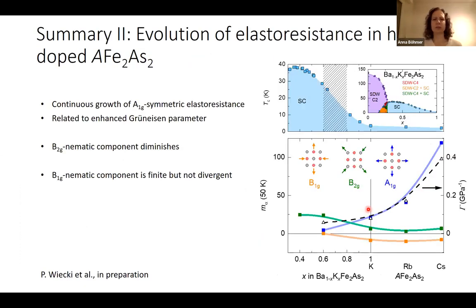So this brings me to the summary of my second part. In this evolution, we see a growth of the A1G elastic resistance systematically towards the cesium-122, which is related to the enhanced Grüneisen parameter, while the B2G simply diminishes and the B1G component is finite but never diverges. Thank you very much.